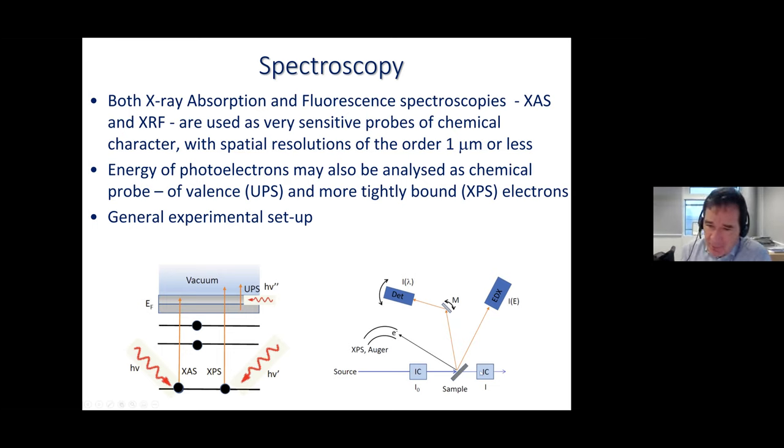And then finally, if the process gives rise to photoionized electrons, we have to have a means of measuring the energy of those electrons. And we do this through the same principle as a mass spectrometer works. So we have a charged particle. In this case, of course, the mass is known. It's the mass of the electron. And actually what we're measuring by measuring the deflection through a given magnetic field is the velocity of those electrons. And this is the basis of, and we'll look at this in a bit more detail later on, the Auger effect, or the application of the Auger effect and photoelectron spectroscopy.